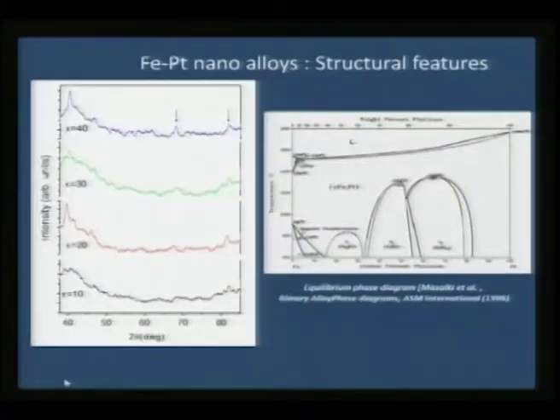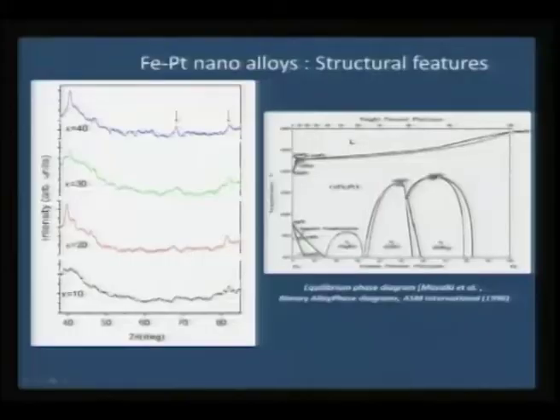but nevertheless they seem to have almost a mono size when prepared. Now if you look at the X-ray diffraction pattern, you can see here they show not absolutely amorphous, but with more and more platinum there seems to be some crystallization process that is happening, but without platinum you can see that this is a typical amorphous phase as seen from the X-ray diffraction pattern, and you can see prominent peaks emerging due to platinum as you increase the ratio to 40% of platinum.